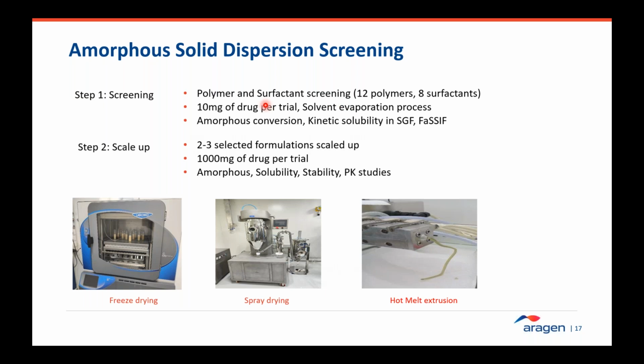So that's the criteria to select the best polymer and surfactants, and then combinations, and they're further screened in multiple levels to optimize the drug load before we go into the scale up stage, where a few formulations are selected for the scale up, optimized. This is not yet process development, it's only a scale up at a very small scale.